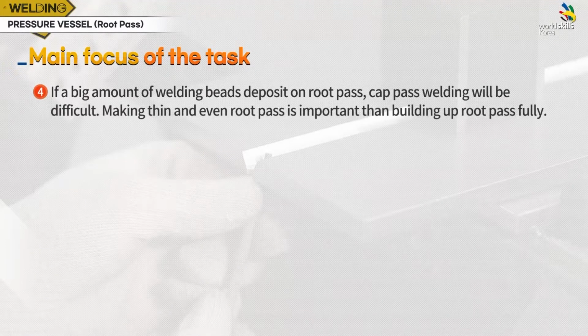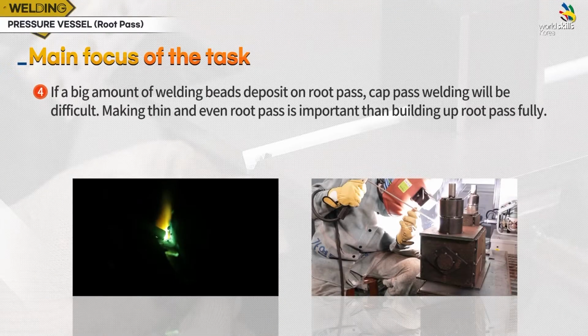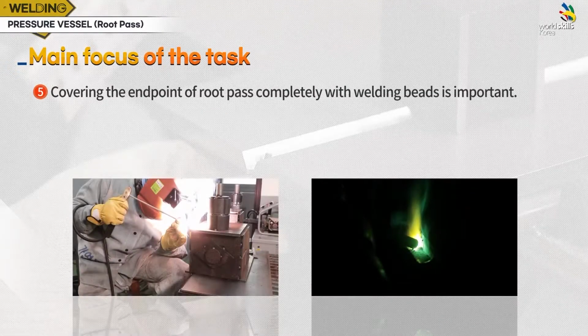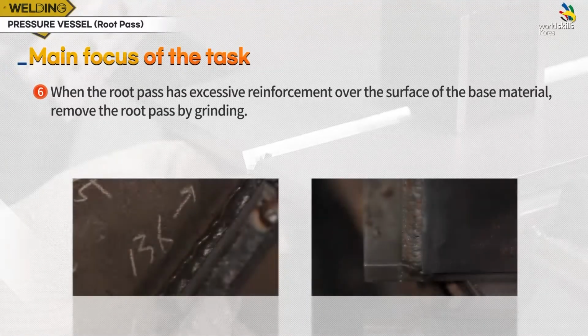If a big amount of welding beads deposit on root pass, cap pass welding will be difficult. Making thin and even root pass is more important than building up root pass fully. Covering the end point of root pass completely with welding beads is important. When the root pass has excessive reinforcement over the surface of the base material, remove the root pass by grinding.